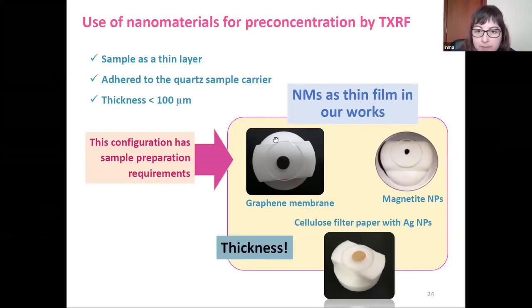In the slide, we can see different examples of our works. For example, this one is the graphene membrane, so we can see that it is very thin, so we have no problems with the detector. Then we have the magnetite nanoparticles and also the cellulose filter modified with silver nanoparticles, which is stuck or adhered to the quartz sample carrier.